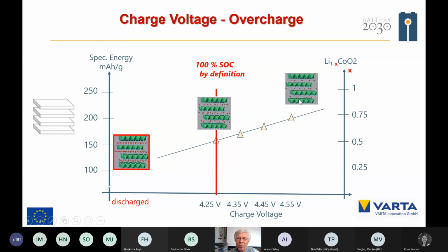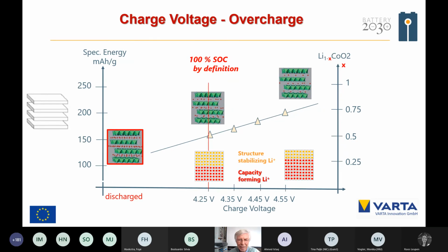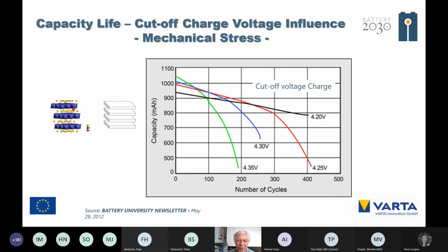Because if you are going to higher values or higher de-intercalation, your structure is no more stable, and the lifetime is decreased. Therefore, all experts give us the upper charge voltage of maybe 4.2 or 4.3. If you are going to higher values, then you are using a part of the structure-stabilizing lithium as capacity-forming lithium. You get a higher capacity, but a lower lifetime, as you could see here, because the structure is starting to collapse if too much lithium is de-intercalated.